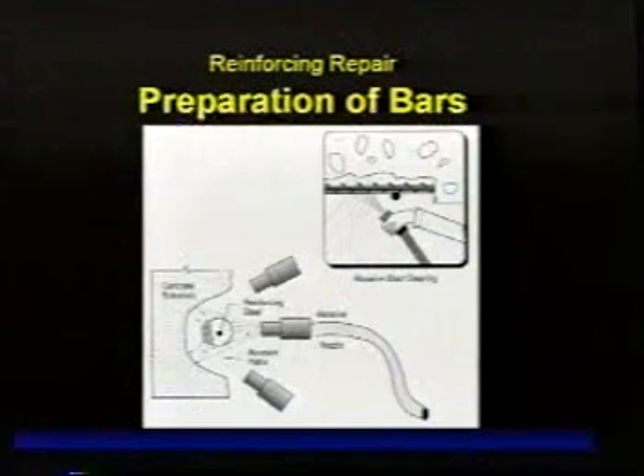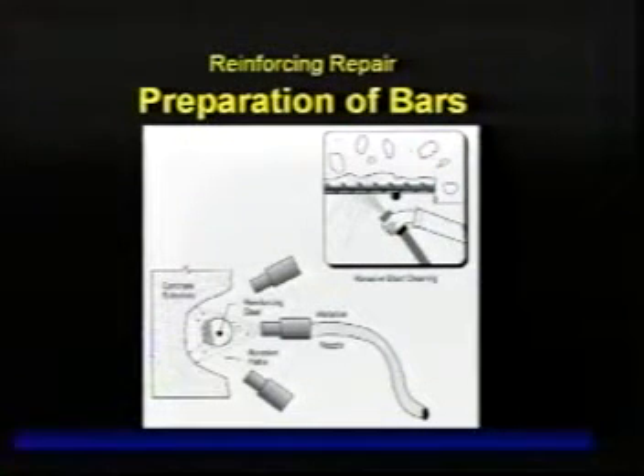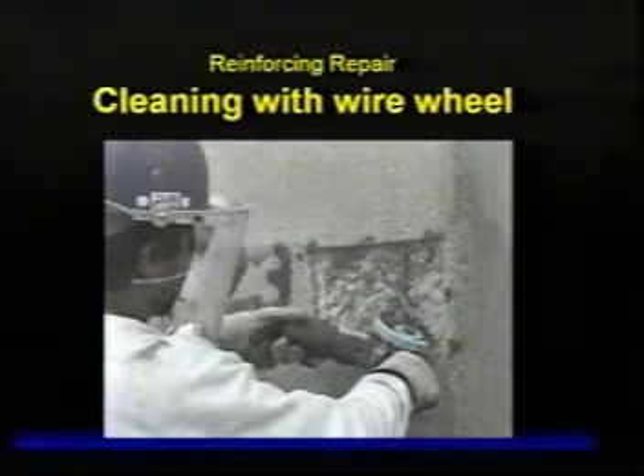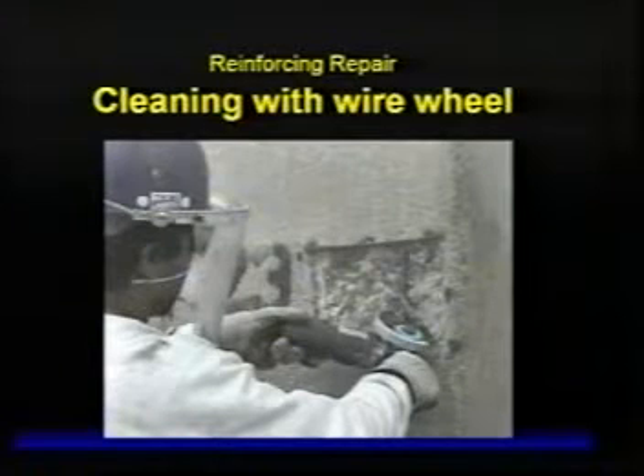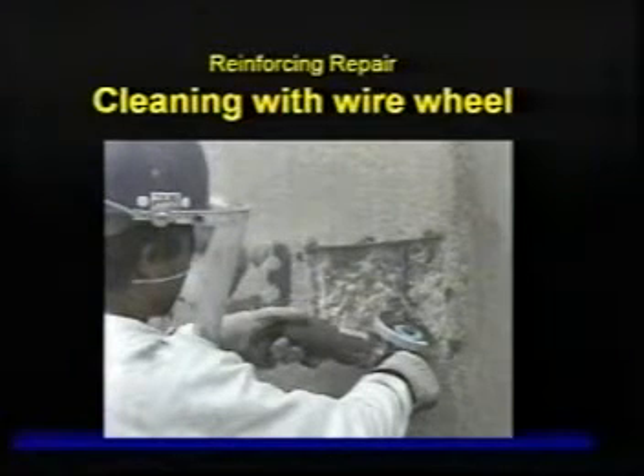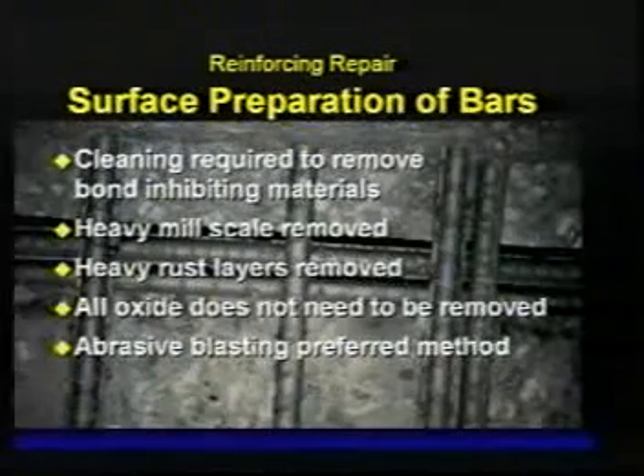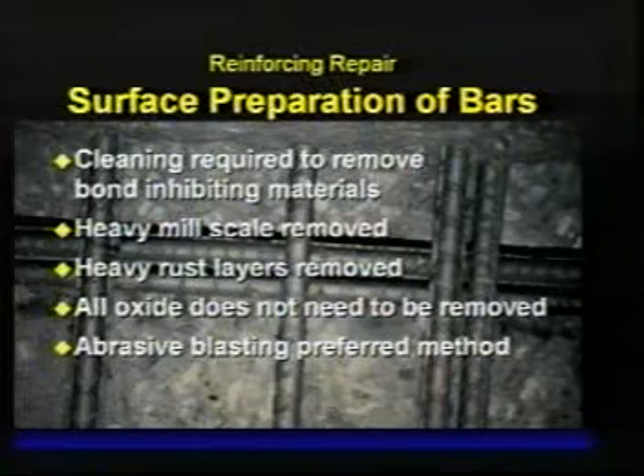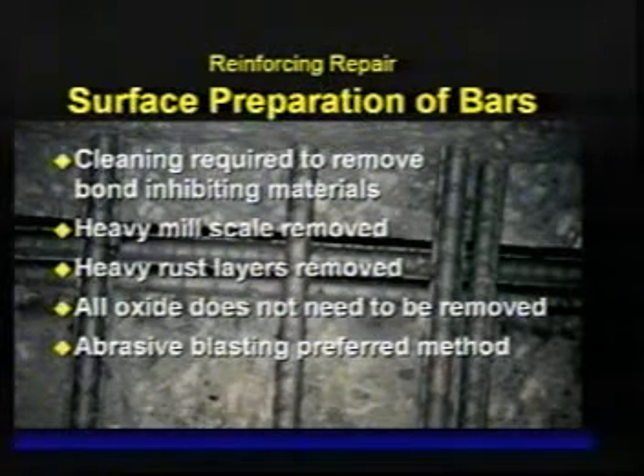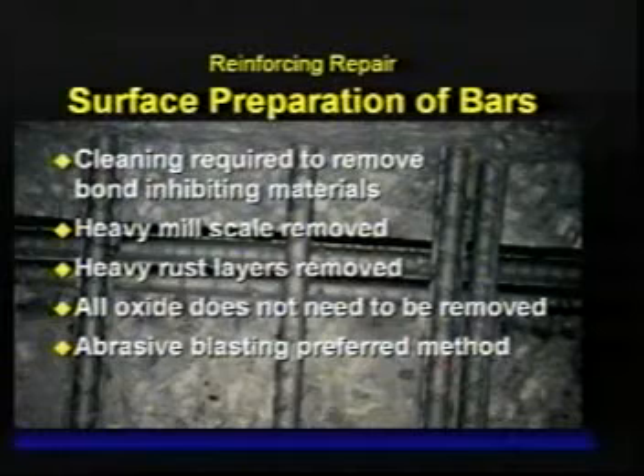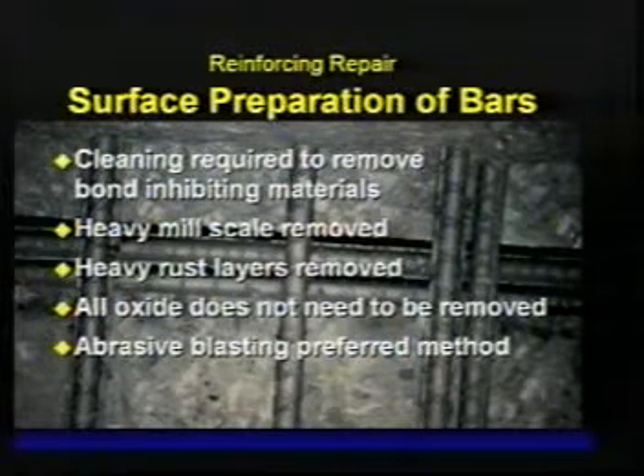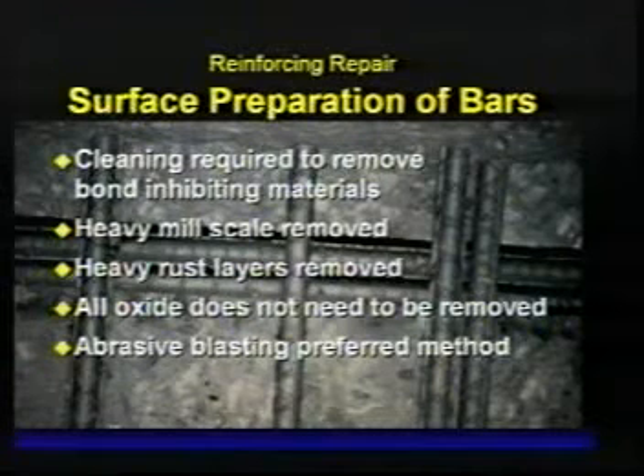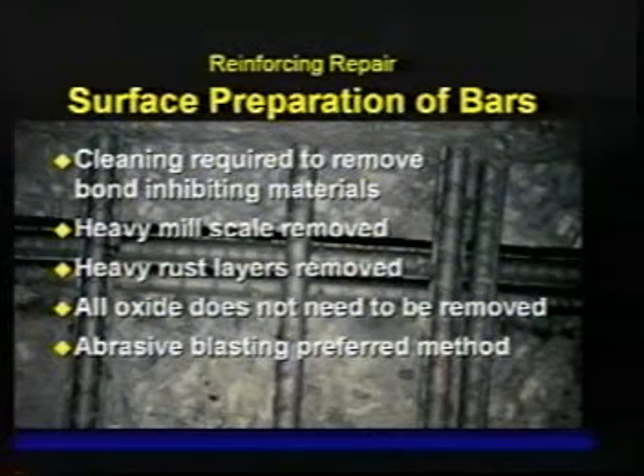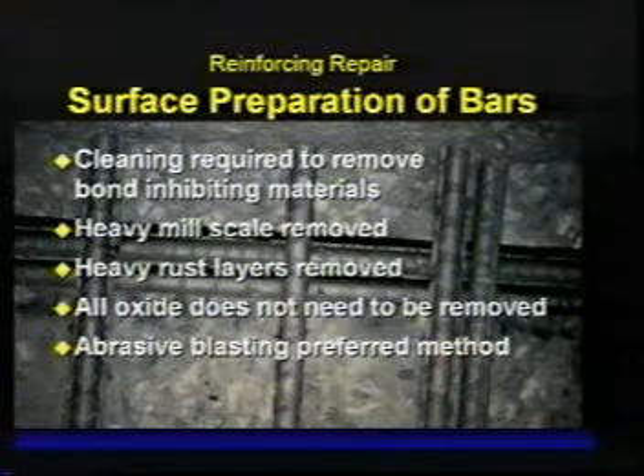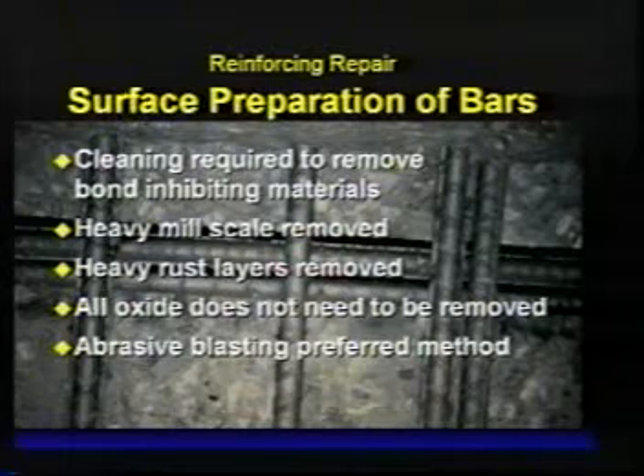The reinforcing steel, generally we're doing these repairs because there's corrosion. The corrosion products have to be removed. And the generally accepted practice is to use methods, whether they're abrasive blasting or, in this particular case, this small repair, we're using a wire wheel, so that we don't have anything that would inhibit the bond of the new material against the reinforcing steel. So that would meet the same requirements of new construction, which is any loose mill scale or any kind of corroded scale needs to be removed, and that's the minimum requirement. If there's a coating being applied, then the preparation system must meet the manufacturer's requirement.